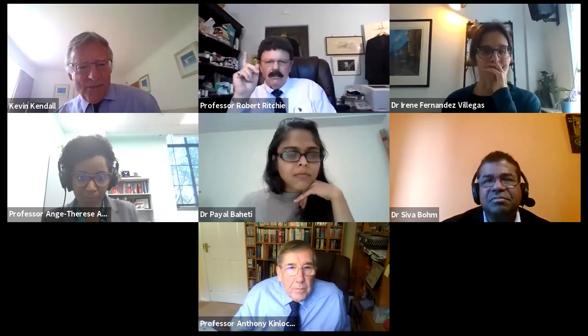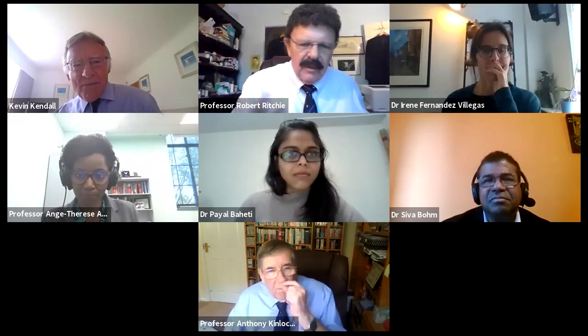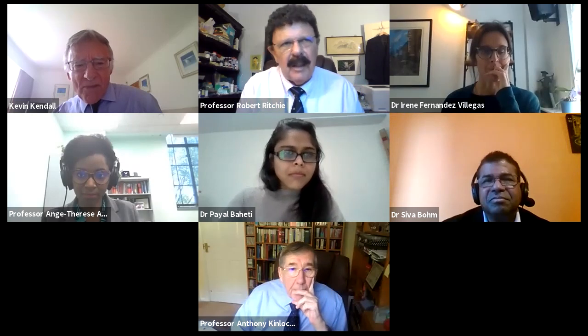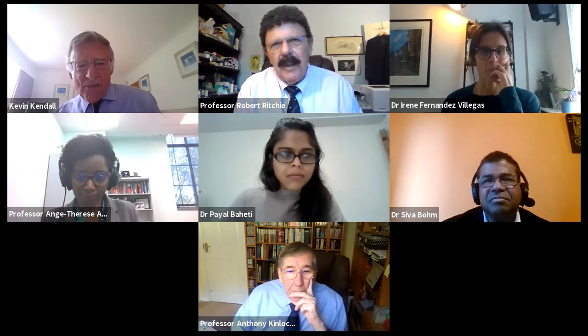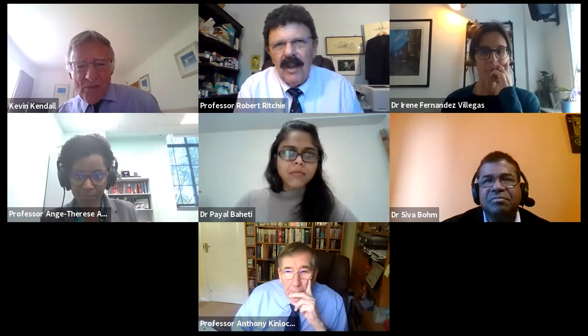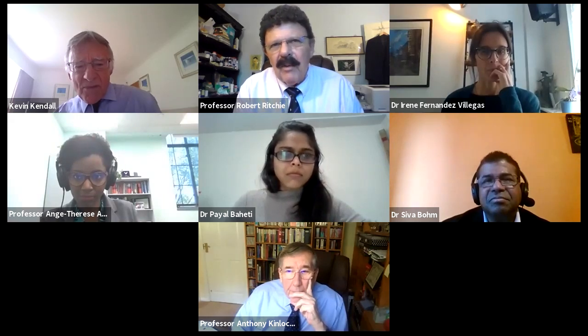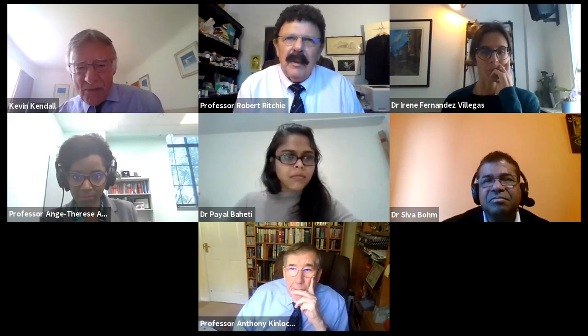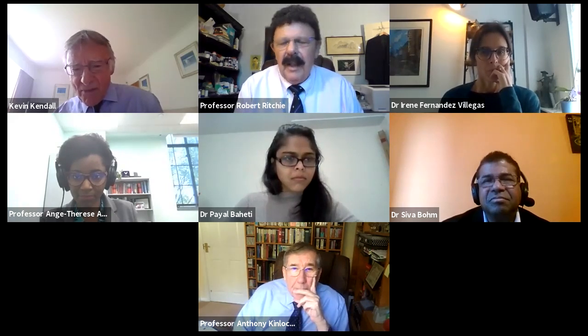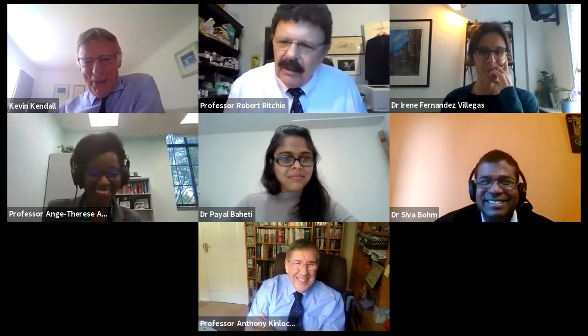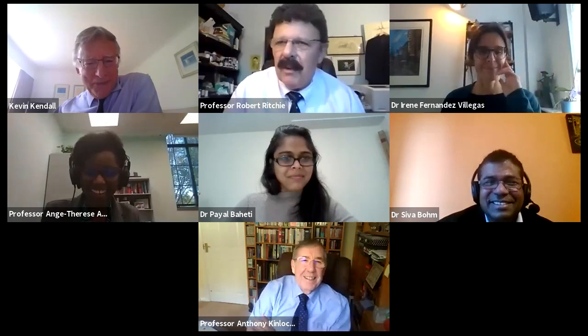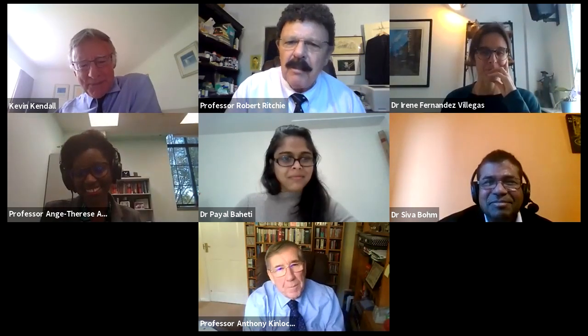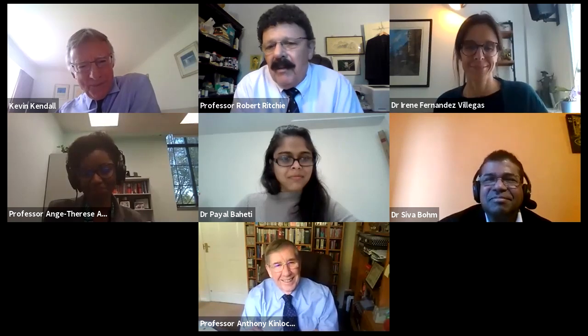Would you care to comment, Rob? I mean, I think this is the inherent problem with fracture mechanics, that if you're measuring something like K1C, then that's pretty robust generally in terms of the initiation toughness. But Joe Gallagher once said, if you can measure K1C in a reliable fashion in a material, you probably don't want to be using that material, because you have to be high strength and low toughness and not too much plasticity. And that's the issue, I think, that you want materials to be on an R curve. You want plenty of plasticity, and that makes them very, very difficult to measure.